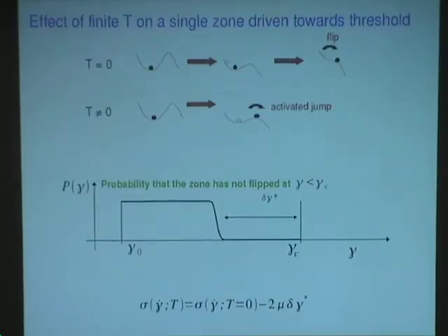Okay, that's ongoing work, to try to characterize via the same type of tools, like diffusion, what happens at finite temperature. What we seem to see, and it's very preliminary, is that if you are at finite temperature, say above half of TG, you don't see any change of this correlation length, because essentially you just shift the gamma criticals.